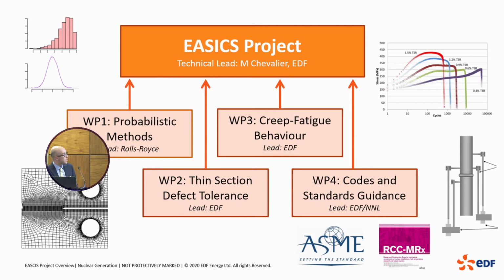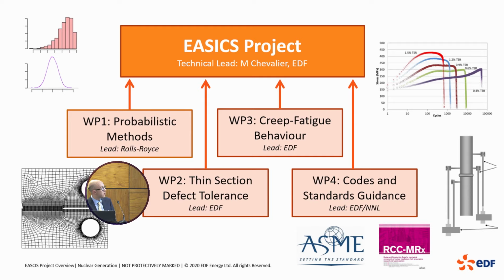Work pack 2 is all around thin section defect tolerance. So a key part of this is looking at the OPEX. So the AGRs are one key bit of OPEX, but there has been a number of high temperature reactors built around the world, Gen 4, typically test type reactors, and the reliability of those has been awful. And the reliability has been awful typically because of heat exchanger problems in a lot of the designs. And that is because you've got creep fatigue interaction, naturally they're thin, naturally they see big temperature cycles, and high temperature degradation, environmental effects, creep fatigue effects, tends to make them a weak location.